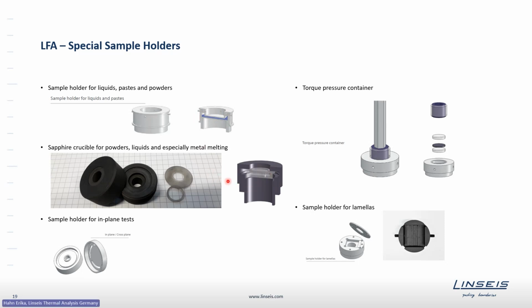In addition to that, we have a specialized sample holder especially designed for the melting of metals. Here we have the carrier. In the middle of that, there's a hole fixed for a sapphire crucible where the sample will be placed. That will be closed with a lid. And then the lid of the carrier will also be fixed and screwed so that nothing can move at higher temperature. Meaning that with these sample holders, one can also start with a solid sample and melt it at higher temperatures. As mentioned, the sapphire crucible is especially suitable for metal melting to avoid too much contact with graphite, as all of our sample holders are mainly made of graphite.